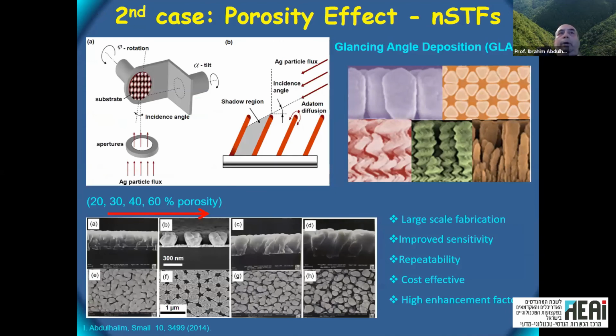Okay, we also mentioned the porosity effect. And actually, we were guided by this correlation between sensitivity and overlap integral. We wanted to prove that the porosity actually improves the sensitivity. So we went into this methodology of producing porous metal by oblique angle deposition.